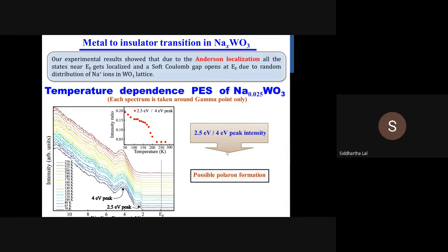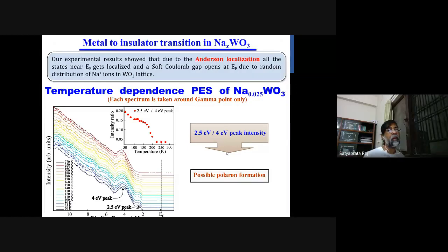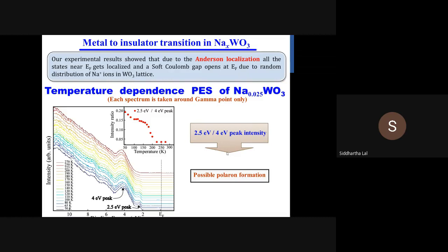No, but you can look for magnetic field dependence. This slide is showing data deeply on the insulating side. My claim is that if you look at the metallic samples for transport signatures like magnetoresistance, there is a chance you might see the destruction of weak localization. But these are dirty metals, so I don't think you can capture weak localization, because the quantum interference will be destroyed by this dirtiness. No, Satyabrata, the weak localization signatures have to be seen on the metallic side, because on the insulating side you will most likely hit the strong localization regime, and it will be very hard to see the formation of those loops.